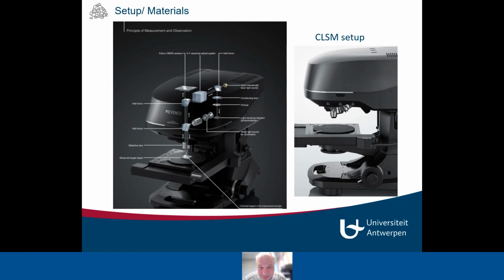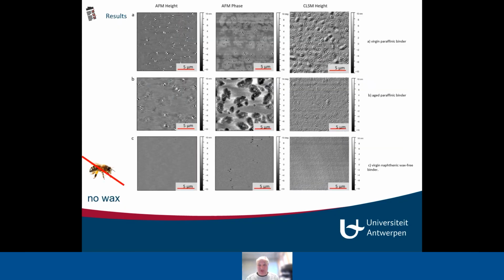So you can work on hard and soft and even liquids. That's all possible. So if we look at some images, on the left-hand side you see AFM. I show two images from the AFM, the height and the phase. George has also already shown some images. These are, I think, the same sets of images. And you see that indeed, if you have virgin paraffinic binder, you can see very similar images of AFM and confocal laser scanning microscope.